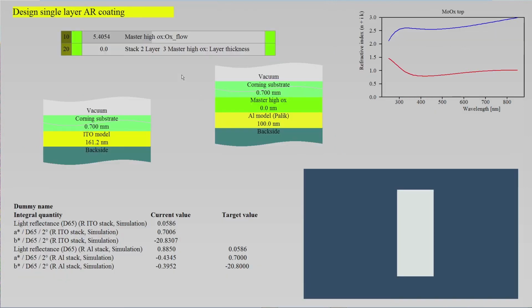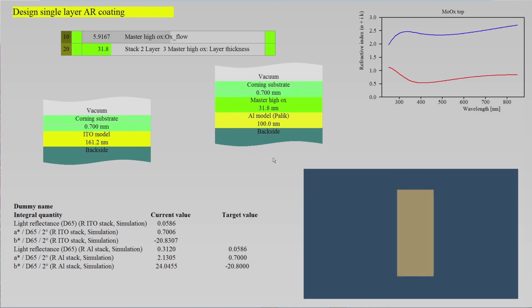Then you just have two parameters when you introduce the anti-reflection layer here between the Corning substrate and aluminum. You have the oxygen flow during production of that layer. You can see here how the optical constants change. If I change this model, it's a smooth transition from metallic to more and more dielectric behavior. And as a second parameter, you have the layer thickness here. And in this graph, I show a visualization of the color.